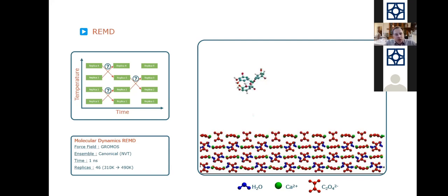So we continue. In order to accelerate the process, we introduce replica molecular dynamics, which means that we use different starting geometries, and we do a combination of all these molecular dynamics. Once we find a better structure, we use that to modify the one which was better before. So we make a selection of the best structures, in order to not go through all the other situations in our molecular dynamics. Maybe you can see this in the video here. On the scheme we started with 4, but in fact we started with much more. The number of replicas equals 46, and we jump from one molecular dynamics simulation to another every time we find a better structure than the one before. And so we refine until we have a better structure. The better structure is when we have an interaction, because we lower the energy considerably.